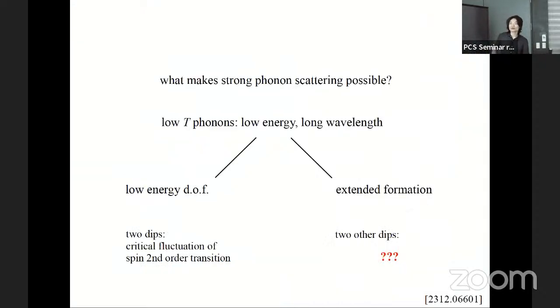Okay, right. So again, we come back to this picture: low temperature phonons, low energy and long wavelength. So the low energy degree of freedom explanation is already involved in the first two dips, right? There's a second order phase transition in the spins, which has some critical fluctuation, which is low energy, and that might have some resonance with phonons, whose details I'm not going into. It's very possible that it will create some dips because the interaction is stronger at the phase transition. Right. The crucial part is to explain these other two dips.